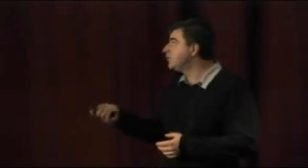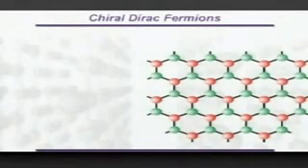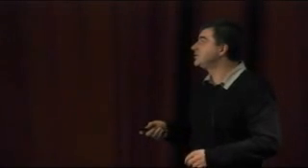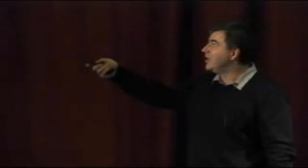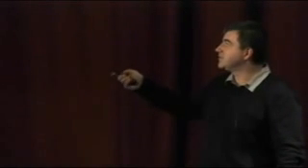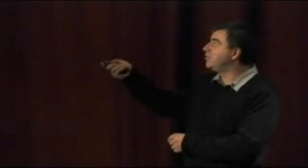Most of those properties are down to this hexagonal crystal structure which carbon atoms form in graphene. It looks extremely simple, but it cannot be categorized as a simple crystal structure. It's not one of the Bravais lattices. It has 2 atoms per unit cell. You can see I colored them differently, the green atoms and the red atoms. Of course, they are of the same color in the real lattice, but you still can distinguish them. All the green atoms would have a neighbor from the top, or the red from the bottom.